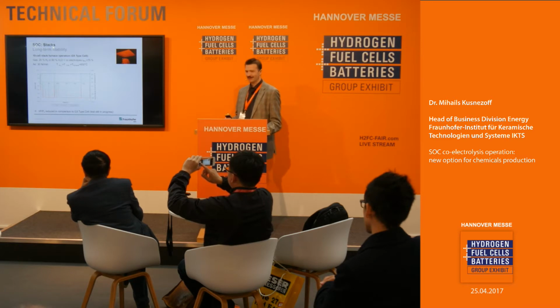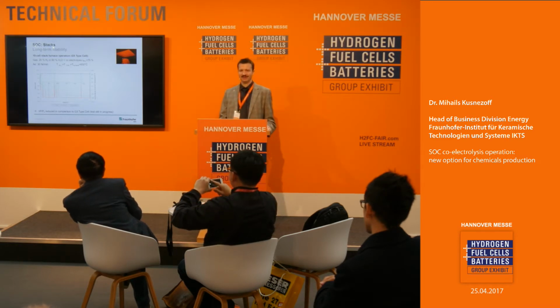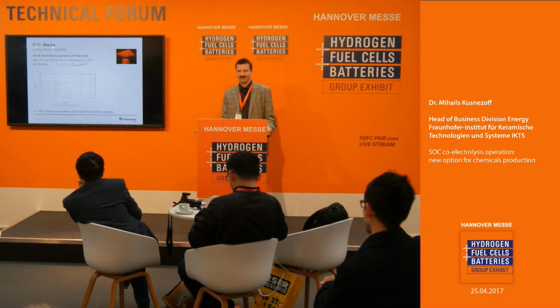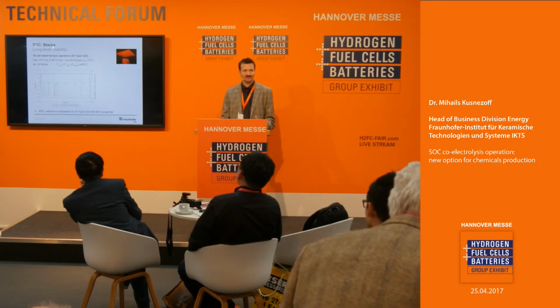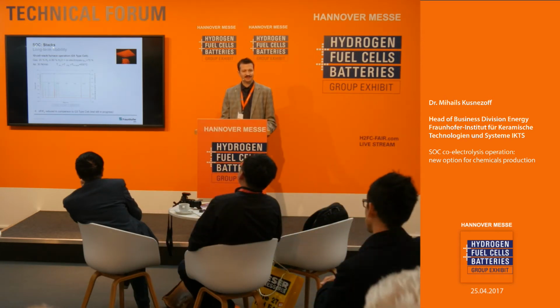We already put the generation 5 cell in operation. And we have seen that we have less degradation with this modified electrode structure, and also at 800 degrees, we don't observe anymore this relaxation phenomena as we have observed with the non-optimized fuel electrode structure.